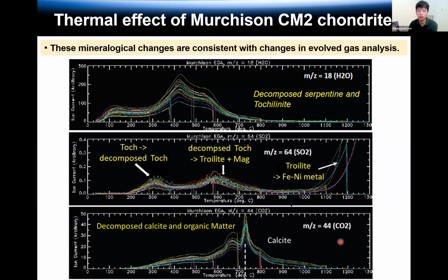And this third graph is showing the CO2 emission. So actually this sharp peak led to the decomposition temperature of calcite. And also this broad hump led to the decomposition of organic material in the Murchison CM2 carbonaceous chondrite.